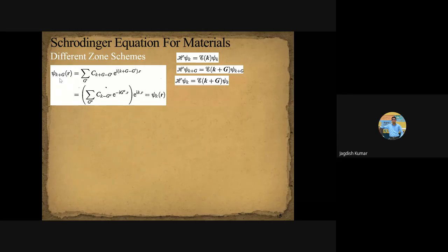So that is why we have a very special interest in knowing the wave vector dependence of the energy of the electron, I mean the energy and its variation with k, which is another quantum number for an electron in a crystalline solid. This dependence of energy on wave vector is nothing but the band structure of the solid, the E versus K relation.